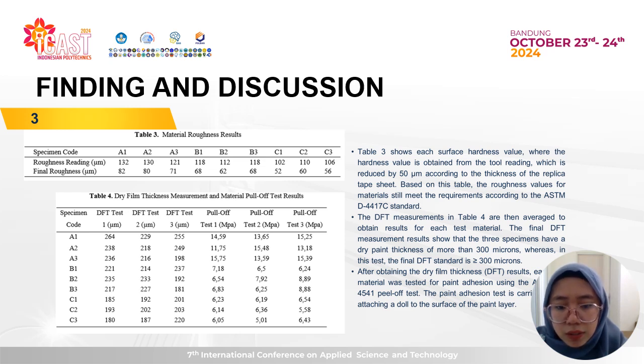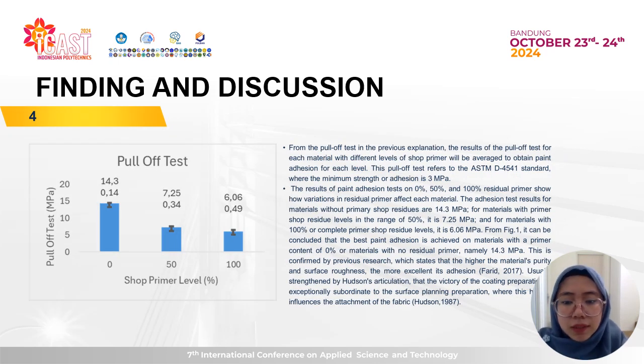The paint adhesion test is carried out by attaching a dolly to the surface of the paint layer. And the result of the pull-off test on the material, you can look at Table 4, beside the DFT test result for each specimen code A, B, and C. From the pull-off test result, as in the previous explanation, the result of this test for each material with a different level of shop primer will be averaged to obtain the paint adhesion for each level. This pull-off test refers to the ASTM D4541 standard, where the minimum strength or adhesion is 3 MPa.